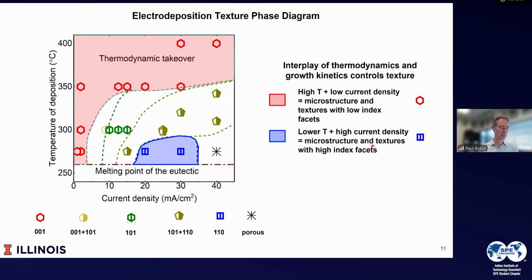So we can build a phase diagram, and this gives you an idea of what will happen at different temperatures and different current densities. The blue is the region that we like the most. It has the proper orientation, but there are other cases where perhaps you want different orientations. What we see is at high temperature it all ends up being parallel. The 001 planes are parallel to the substrate, and we would call this thermodynamic takeover. That's the lowest energy. This is a kinetically trapped orientation here in blue.